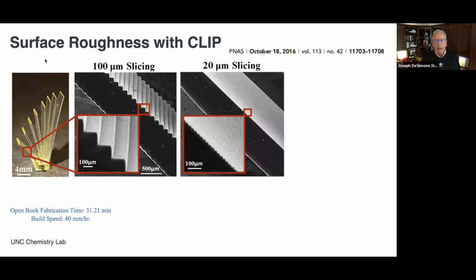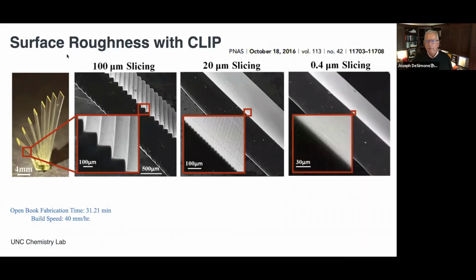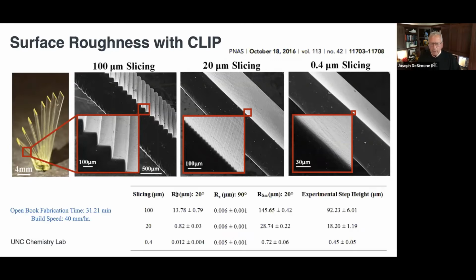Well, we could divide that image 5 times more frequently at higher resolution. And all that means is that the images are changing faster, right? And you're just putting 5 more slices into every 100 micron slice. Well, we can go even faster and at a higher resolution. But these are all done at the same print times. We're just varying the images, right? So if you wanted to do a traditional layer by layer approach and you went from 100 micron slices to 1 micron slice, you would slow it down by a factor of 100. Here, they're all at the same print speed. We're just changing the images. And that's what continuous processing allows you to do.